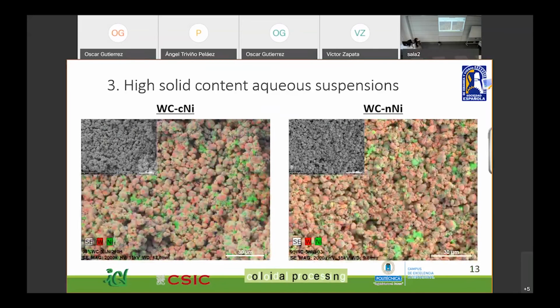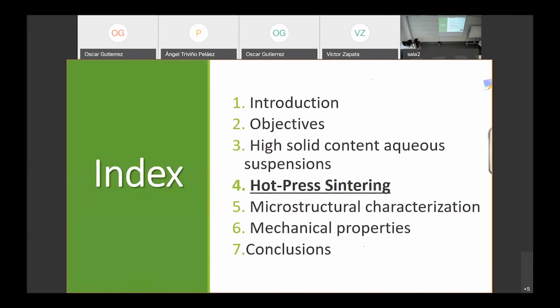From that point, the powders were dried, and here there's an EDX analysis of the processed powder. In the mapping analysis, we could appreciate in green, I hope you can see it well, that the nickel powders in both samples are very well dispersed. After that, we consolidated our structures by doing a hot press sintering process.